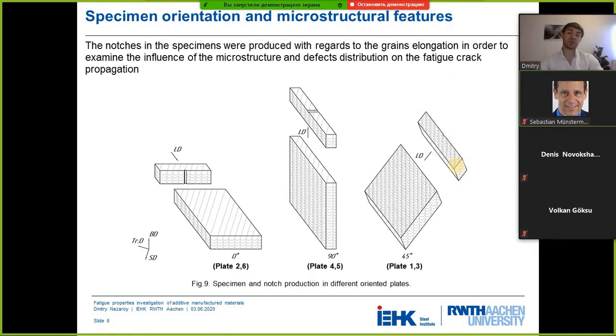But before creating the notch, the microstructure of the given plates should be taken into consideration. In this experiment, we received 6 plates. Plates number 2 and 6 were printed flat on the surface, and therefore the notch was produced in such a way that the crack propagated perpendicular to the building direction.